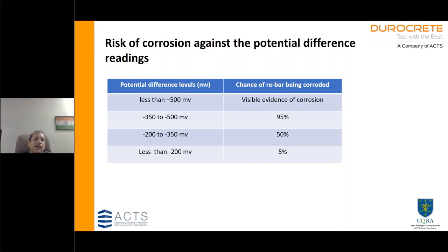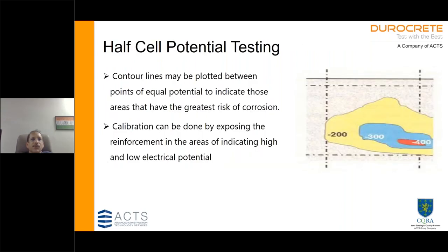But if it is between 350 to 500 millivolts, there's a 95% chance of corrosion. If it is between 200 to 350 millivolts, there's a 50% chance of corrosion. And if it is less than 200 millivolts, it is a 5% chance of corrosion. So you can use half cell to do contour lines.